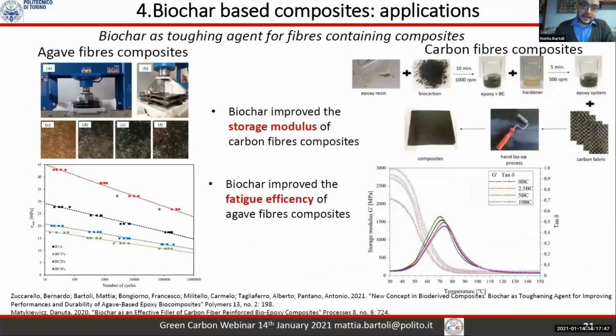From these studies, we came to the applications. Firstly, biochar could be used as toughening agent for fiber-based composites. As Matykiewicz showed for carbon fibers, the addition of a very small amount of biochar could enhance storage modulus, decreasing the brittleness of the composites. Similarly, fatigue tests that we did for agave fibers composite after the addition of 2% of biochar show a great enhancement of durability of this kind of composites.